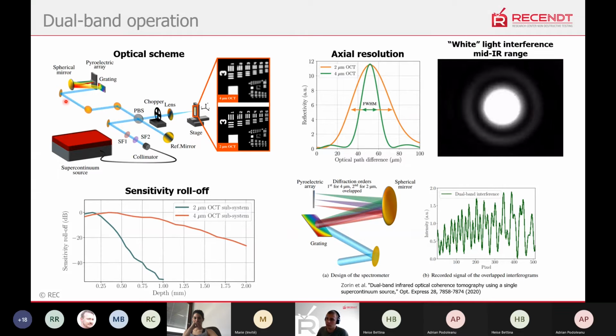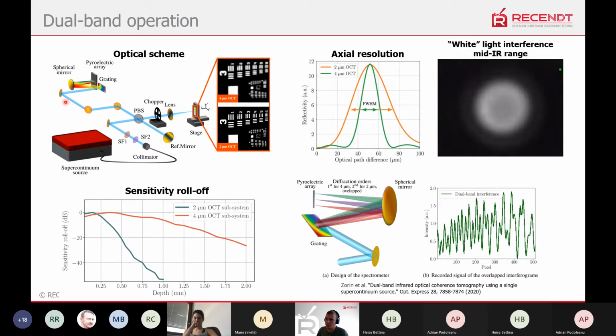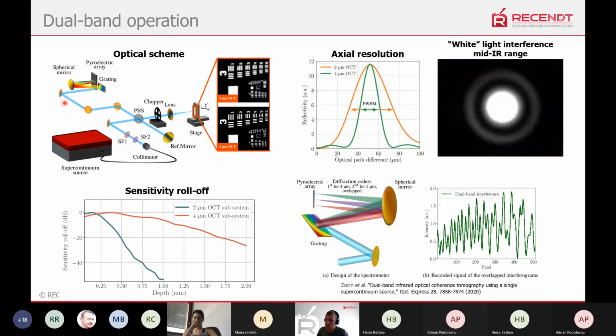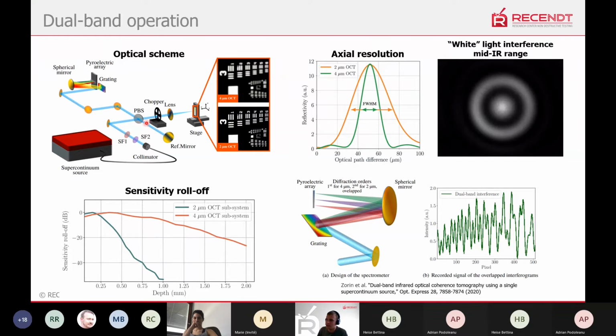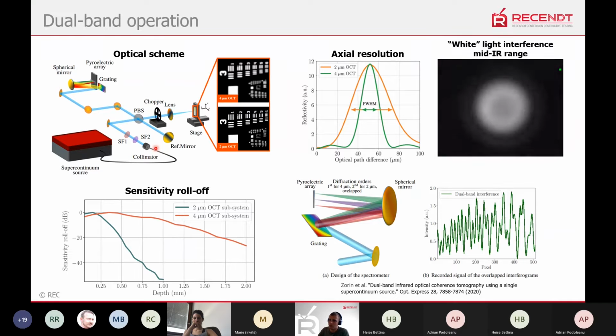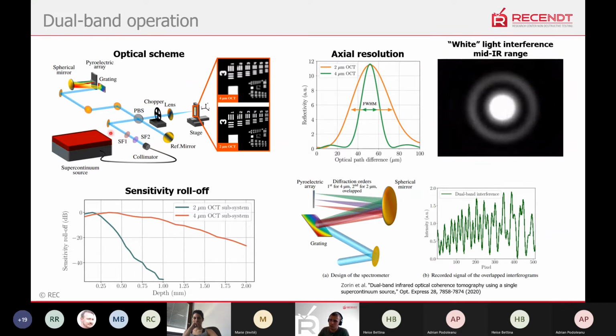So this is first of all because we have a very broadband light source, so we have double wavelengths in the spectrum. And then for a standard grating spectrometer, you would have this. So actually, I had another lens before. It was a doublet, and I saw some ghost effects, some ghost interference, and I tried to get rid of it. But finally, it became clear that actually it's a second diffraction order at 2 micron, which overlaps with our first diffraction order at 4 micron, and it can give me some benefits.